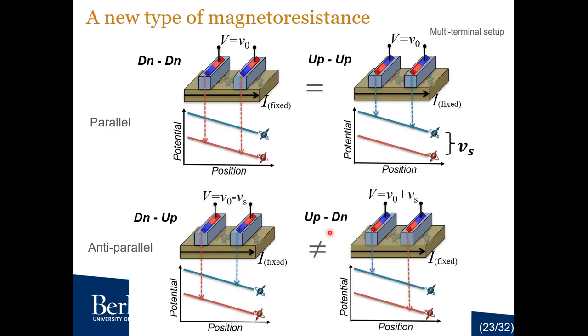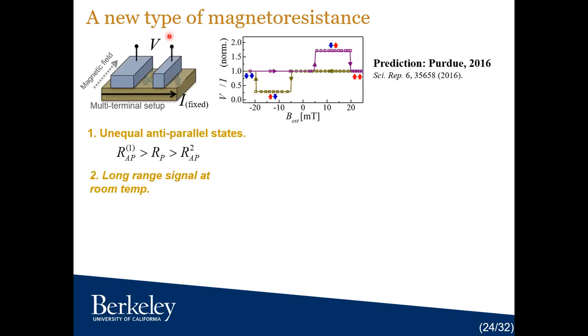So how do we see that experimentally? We can make one of the magnets much bigger than the other so that when we apply an external magnetic field, one of them switches earlier than the other. Thus, we can see all possible states: both down, both up, down-up, and up-down. What we expect is that the parallel states are equal, but the anti-parallel states are unequal. One of them is lower than the parallel states, and the other one is higher than the parallel states. And this is observed in a multi-terminal setup.